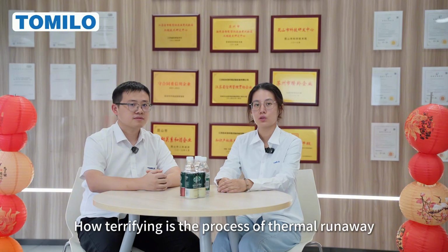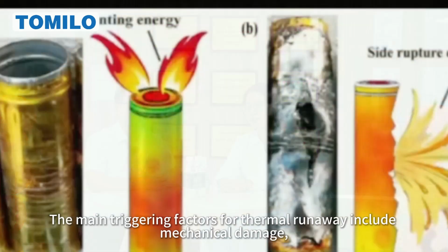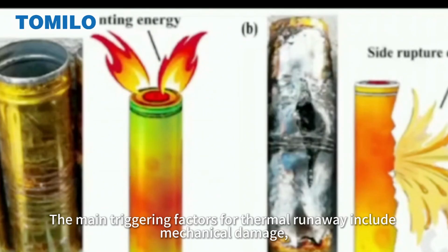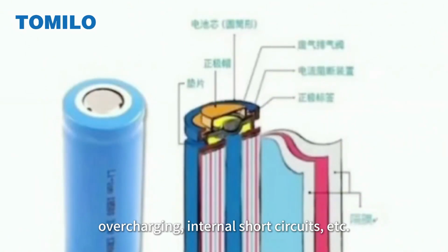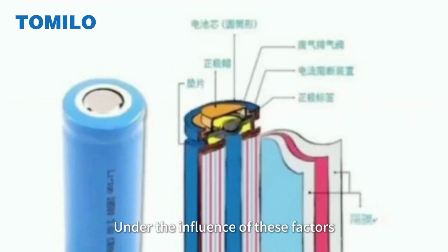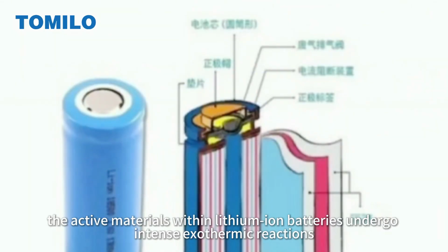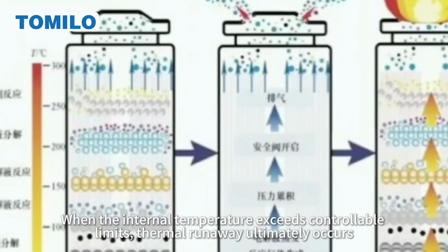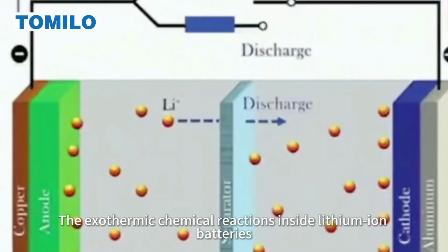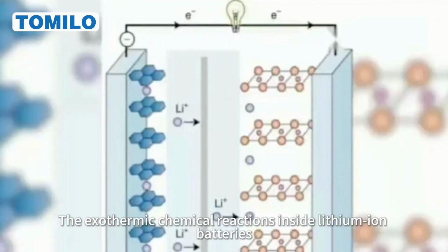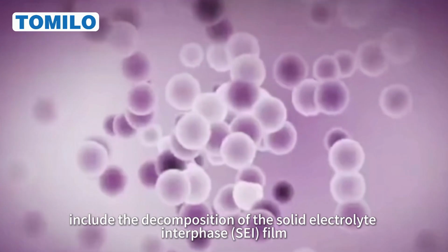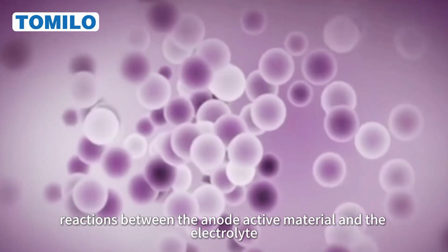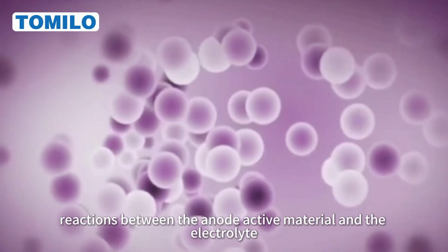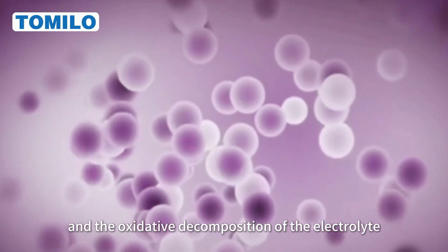How terrifying is the process of thermal runaway? The main triggering factors for thermal runaway include mechanical damage, overcharging, internal short circuits, etc. Under the influence of these factors, the active materials within lithium-ion batteries undergo intense exothermic reactions. When the internal temperature exceeds controllable limits, thermal runaway ultimately occurs. The exothermic chemical reactions inside lithium-ion batteries include the decomposition of the solid electrolyte interface, SEI film, reactions between the anode active material and the electrolyte, and the oxidative decomposition of the electrolyte.